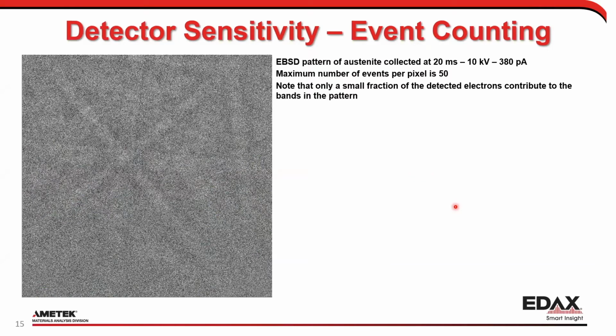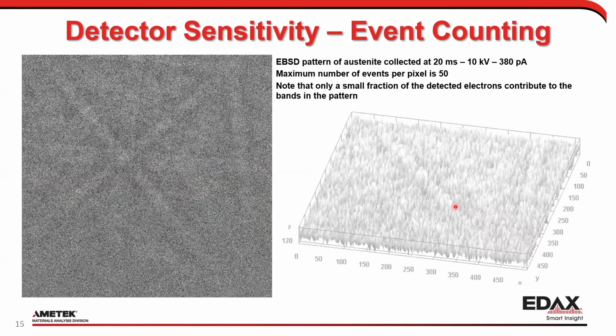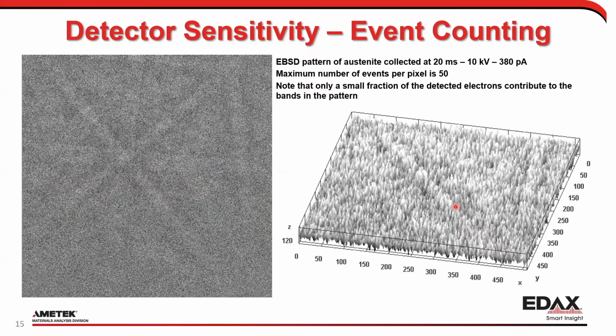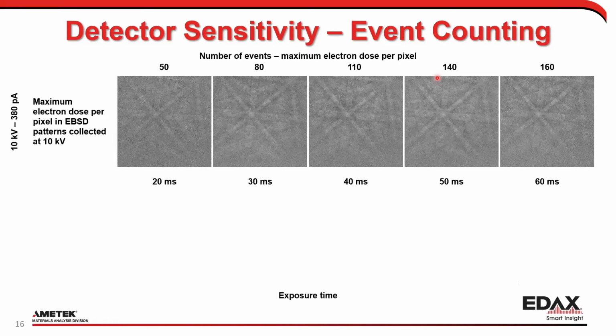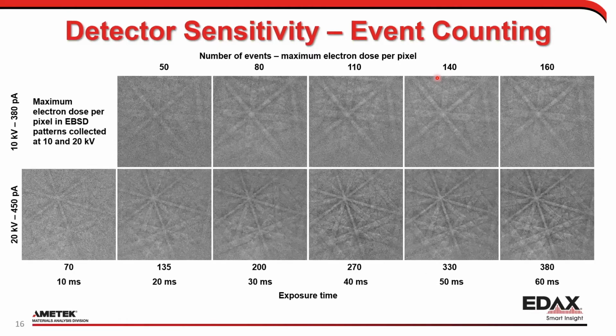So here you can see that I only have 50 maximum electrons. But even with that 50 max electrons, I have enough electrons over background to say I have patterns here that are indexable. This is a perfectly indexable pattern at 50 electrons captured per pixel of the detector. What that means is you can go further down the line, but in this case it shows the other way around, where I can do 50 electrons or I can go to 380 electrons per pixel, and I get better and better pictures.